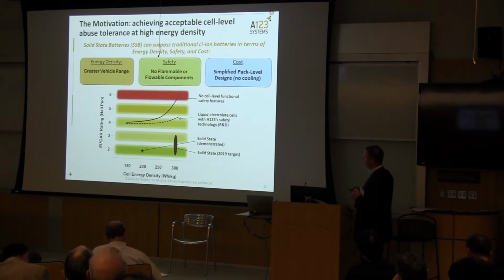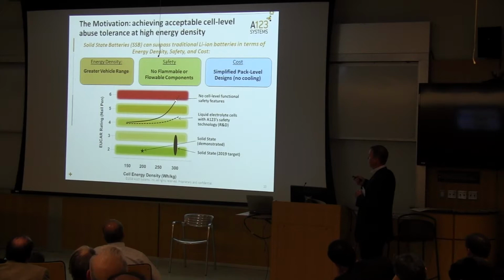And so I like this chart to really highlight what we're seeing. It's the EUCAR rating. 2 is great, 6 is bad. That's pretty much an explosion, as a function of the cell energy density. So for the cells that we make, you could see from 150, which would be something like an LFP or a 111 cell, going to pushing 300, which again is 80% nickel or higher. If we just use off-the-shelf materials, we can't make anything as we approach this energy density that's any lower than EUCAR 6. When we start utilizing our modified cathode materials, we can drop this, and we teeter back and forth between passing and not passing.